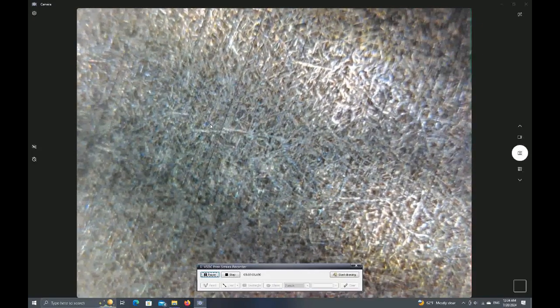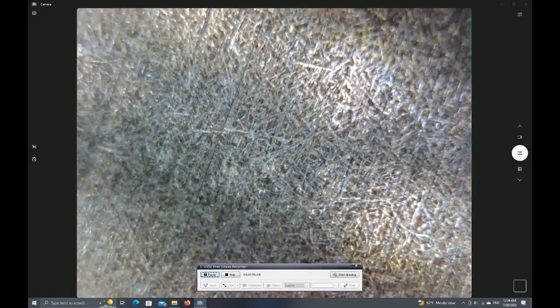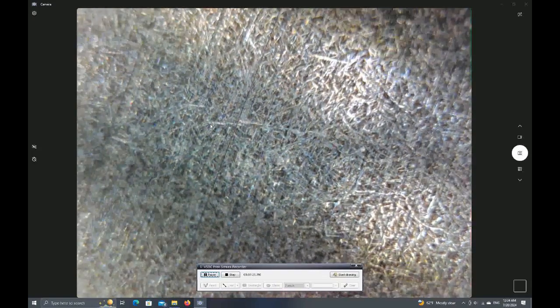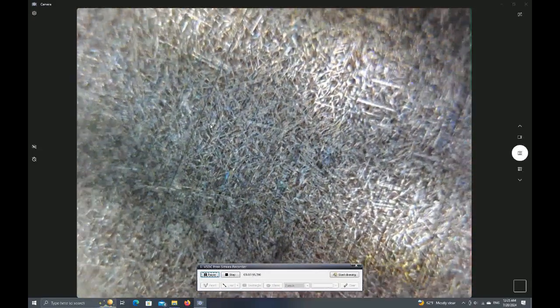Now, typically in metallurgical analysis, you grind up to a micron finish and etch with the same nital acid, and doing so gives you basically no defects on the micro features, the microstructures of your steel. And I did not do that. You can see straight lines running from kind of top center, maybe 1 o'clock or 12:30 if you look at a clock, and then going down to about 6:30. These straight striations are scratch marks from the 320 grit belt, and you can kind of see those features reflected throughout. But you can certainly see microstructures beyond those scratch patterns.